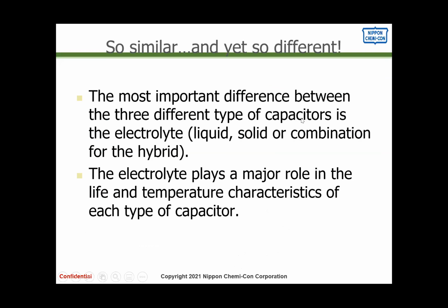Yeah, that's good, George. So, as I mentioned briefly before, the most important difference is basically the electrolyte type. And the electrolyte type will determine or force changes to the foil and the paper. And of course, the electrolyte itself plays a major role in the capacitor and how the capacitor behaves over life and how the capacitor behaves over temperature. One rule of thumb is that as the voltage increases on the capacitor, the electrolyte gets thicker and thicker. The other truth about capacitors is that a liquid is affected by temperature, especially for the electrolytic capacitors. And a thinner electrolyte typically has a lower ESR versus a thicker electrolyte.